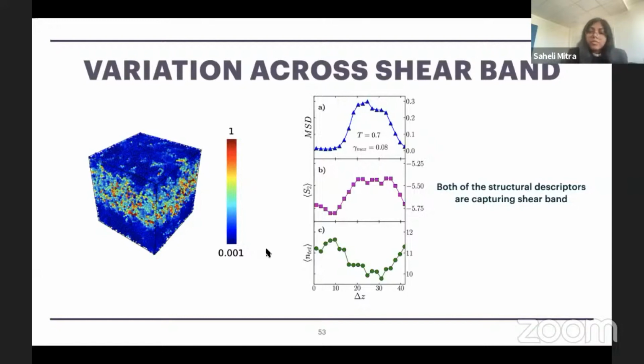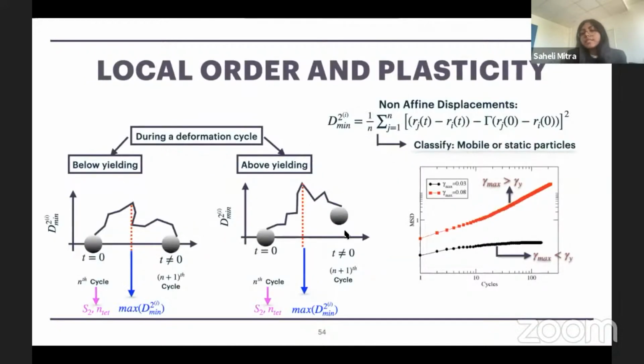So next we want to see what happens to the plastic rearrangement in the course of cyclic deformation in the steady states of shear. In the steady states of shear, as we explained earlier, from one cycle to the next, particles come back to the initial position if the shear amplitude is below yielding, and they cannot do so if the shear amplitude is above yielding. So during the deformation cycle, each particle can rearrange though, and we want to classify the particles going through higher rearrangements and those going through lower rearrangements by computing the non-affine displacement. For each particle, we compute the non-affine displacement during the course of cyclic deformation, and we record the maximum rearrangement it has gone through.